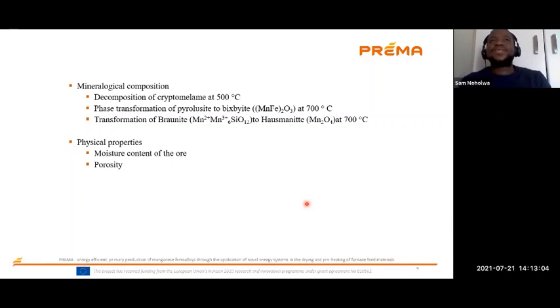Then we go to physical properties. One of the physical properties that affect the decrepitation index of this ore is the moisture content. These ores differ in terms of porosities, and some pores within these particles may be closed pores and others may be open pores. Now, you may have moisture trapped in these closed pores. When you have moisture trapped in these closed pores and you heat it, obviously the vapor pressure of that moisture in the closed pores will rise. Sometimes as the ore is being heated further, the vapor pressure of that moisture in those pores may rise high enough to cause rupture in these particles and create porosity.